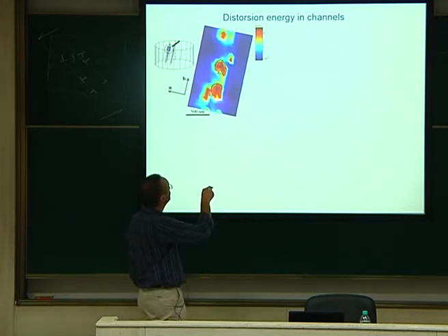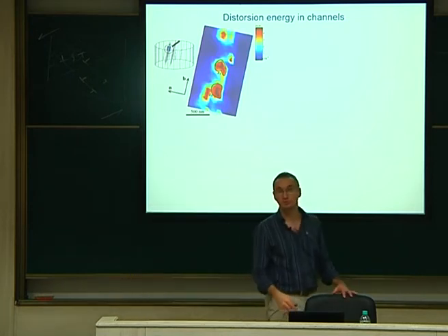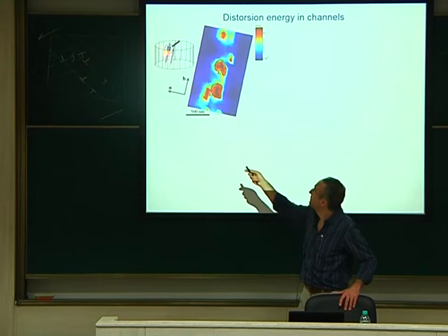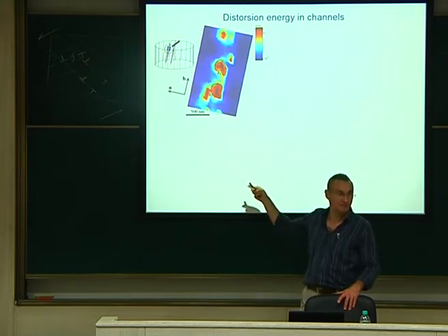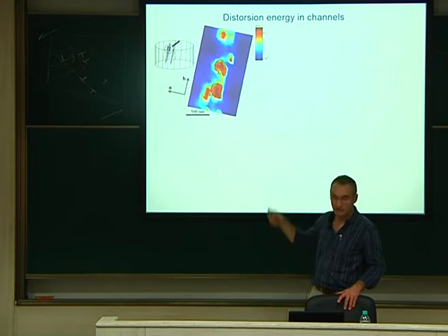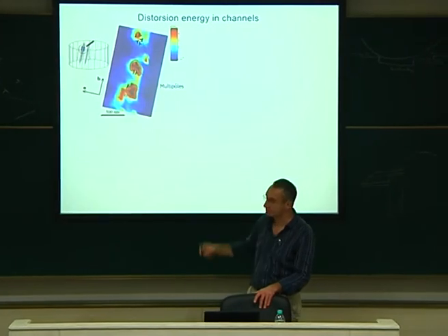And you see some highly energetic zone here, which corresponds to the dipoles. It's exactly the place where you have some multipoles, those are the prismatic loops. Prismatic loops are located at that place. This is why you have a large energy at that place, large stress. So this is the dipole, they are like this, okay?